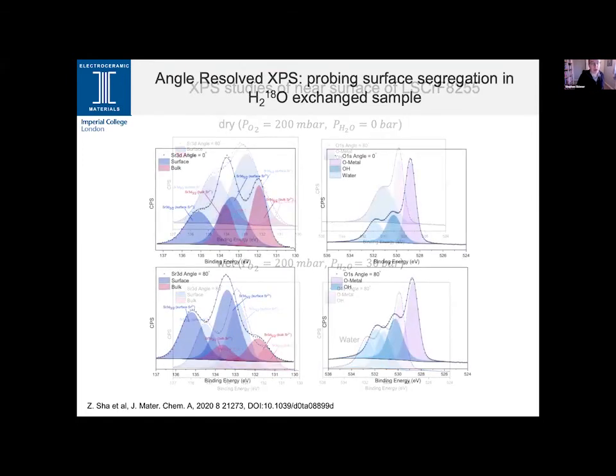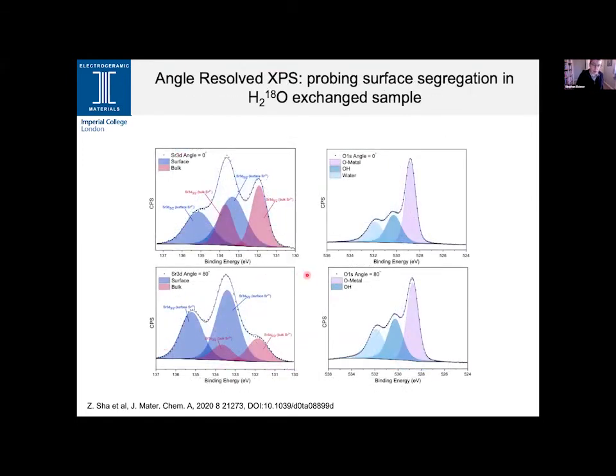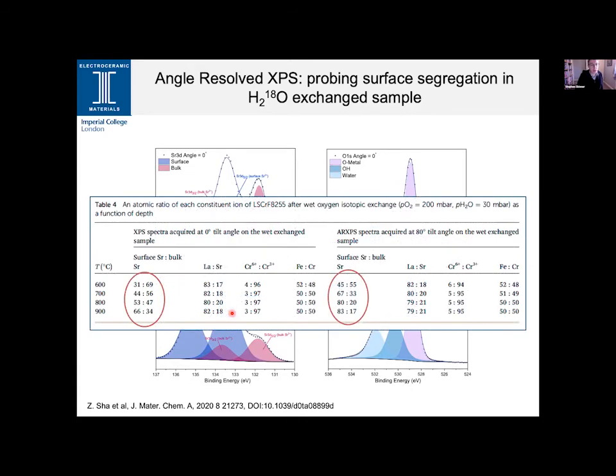If we then compare that to the situation where we have the normal angle, so the penetrating XPS measurement, compared to the angle resolved, we can see clearly that there is a difference between what would be the bulk composition and the surface composition. So we can clearly see significant strontium segregation. And we can go further with that and quantitatively analyze those XPS data. If we do so, we can then determine the ratios of the constituents in this 8255 composition as a function